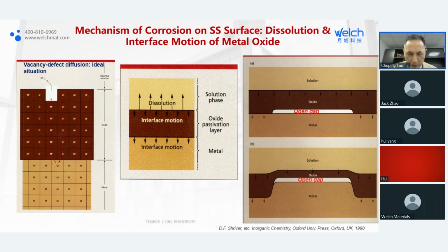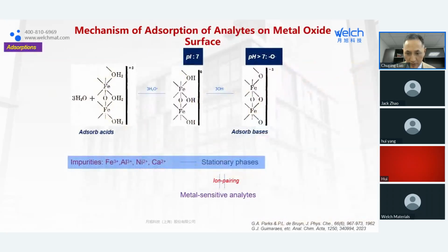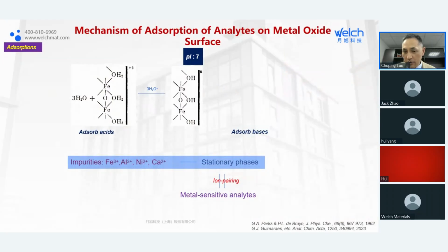All right, so since there's a pI for these oxide compounds, when the pH is less than the pI, say 7, the surface becomes positive. So what's going to happen? This is positive, so it will adsorb acids. Another way, when the pH is higher than 7, you get a negative surface, and a negative surface can adsorb base.